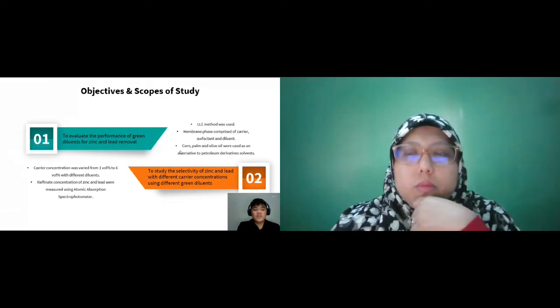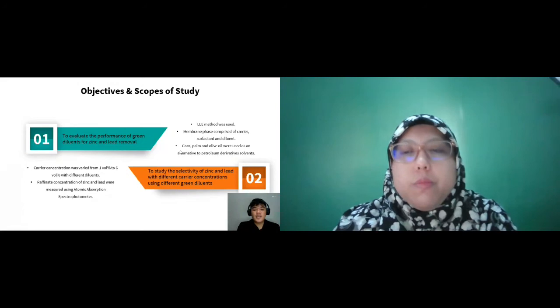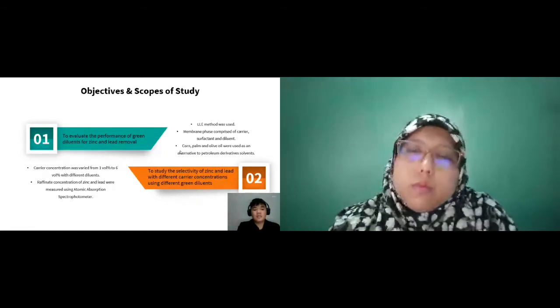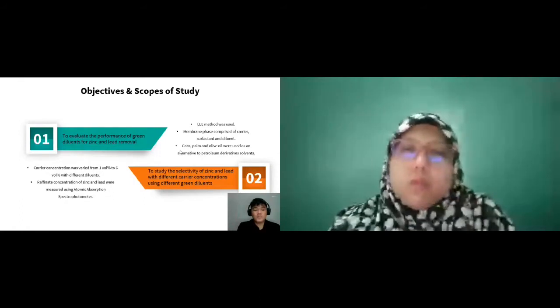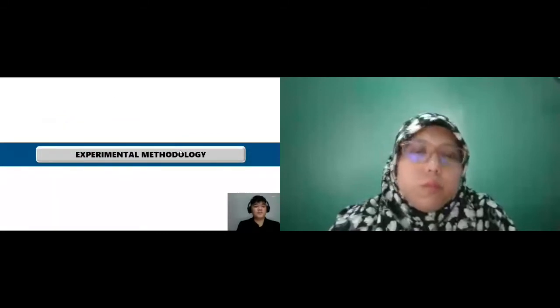The second objective is to study the selectivity of zinc and lead with different carrier concentrations using different green diluents. The carrier concentration is the parameter that will be studied in this project. It is to observe its effect on the lead and zinc removal while keeping the other parameters constant. It was varied from 1 volume percent to 6 volume percent using different green diluents. The raffinate that was produced from this process was measured and analyzed using atomic absorption spectrophotometer.